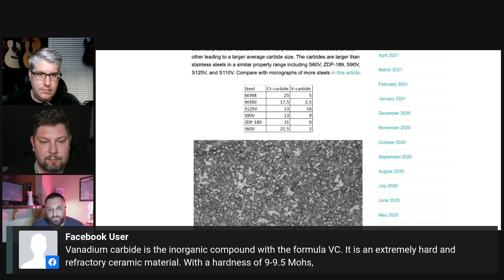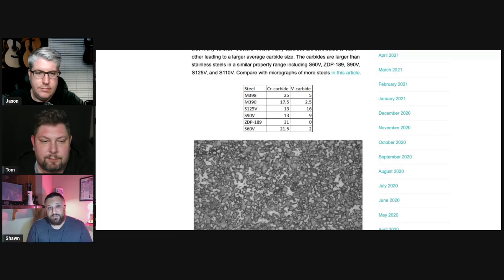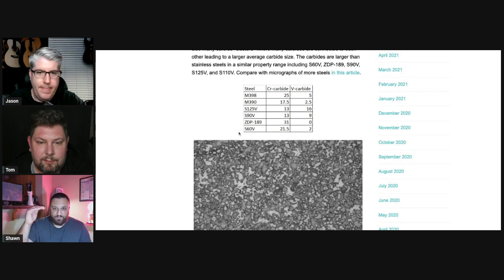It depends on the chemistry of the chromium carbide, also the direction. It's anisotropic, meaning depending on what direction you measure it, it could be harder in one direction versus another, because we're getting down to the atomic scale and things are kind of wacky. But that's why it's difficult to get truly concrete hardness values if we really get into the weeds with it, and we start getting into the stoichiometry of these carbides. But the point is that vanadium carbides are always going to be harder than chromium carbides.